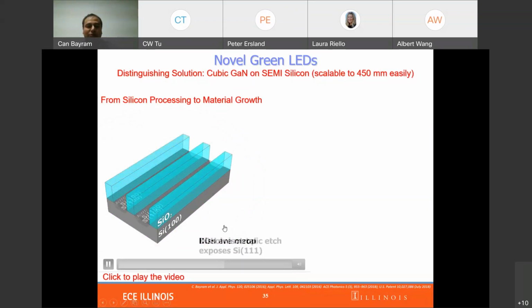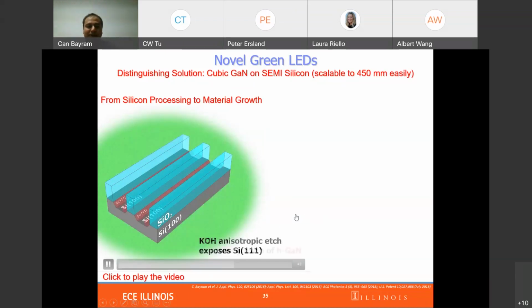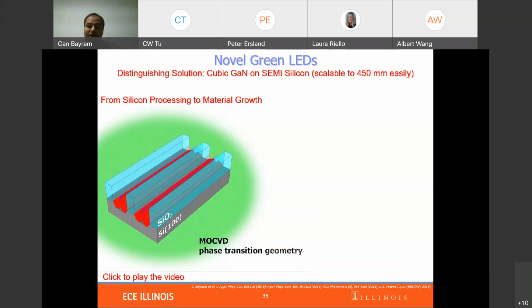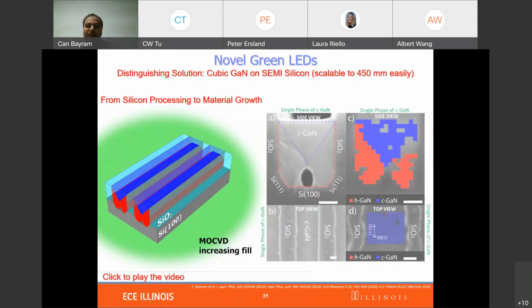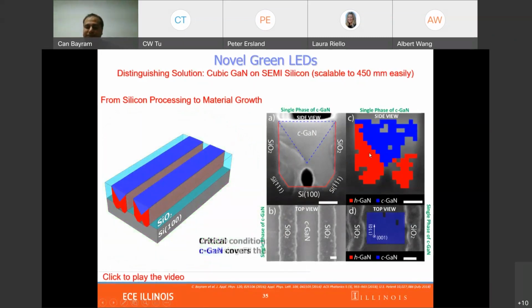And then we are going to start our selective deposition technology, where we can nucleate hexagonal gallium nitride on silicon 111 facets, and when they meet crystallographically, organically, naturally, the cubic gallium nitride forms in the groove and continues to grow as follows.